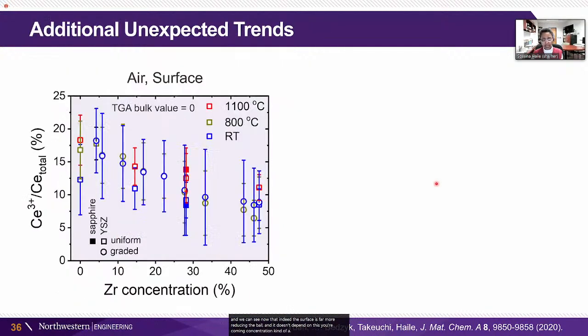Kind of a surprise. Now, as we go to the case of a far less reducing condition, in fact, just the air condition, and we measure it at 3 different temperatures. Here is another huge surprise. First of all, we can see that the cerium 3+ concentration, in fact, declines with increasing zirconium concentration. This is the exact opposite of the bulk.